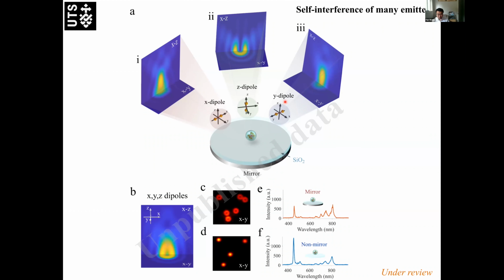One more thing I want to mention about tracking is that we can also use PSF engineering to achieve interesting high resolution XYZ tracking. For XY, you can just use the location to analyze, but for Z, you can modify the PSF. We found one really efficient way to modify the PSF from a single emitter, which is self-interference. If you put an emitter on top of a mirror at a controlled spacing, the emission will interfere with itself. And for different dipoles, the interference pattern is quite different.